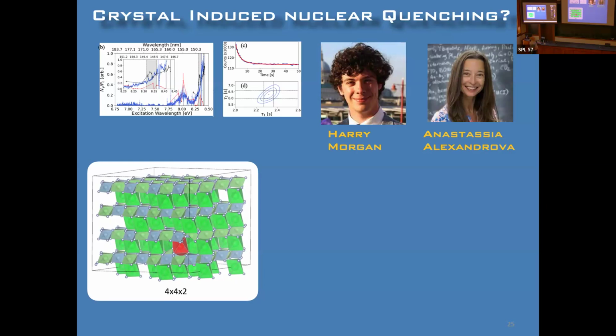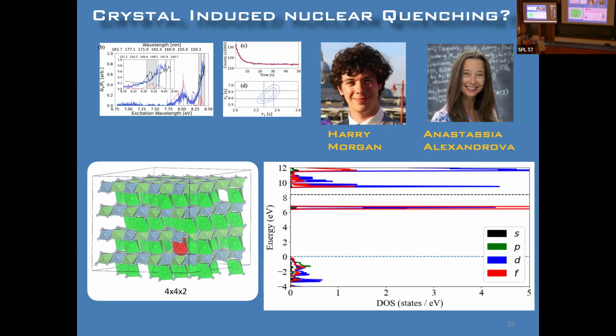But you know, DFT is always troublesome. I think that's what the T is for. The results I'll show here, this graph is what we call a projected density of states. These are the electronic density of states projected onto thorium-centered orbitals. These are the electrons we mostly care about because they're the ones that are going to talk to the thorium nucleus. You can see some structure. This is the valence band, this is the conduction band, a 10 eV gap. Then depending on the configuration, you can get these in-band states that are just defects associated with doping thorium into the crystal. Thorium is a 4+ charge replacing a strontium, which is a 2+, so there's some extra fluorines that appear and the crystal has to bend a little bit to accommodate it. And you get these defects.